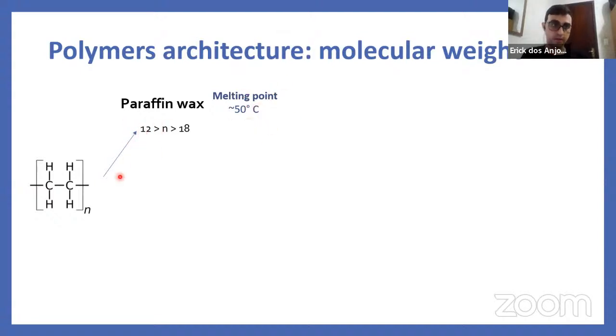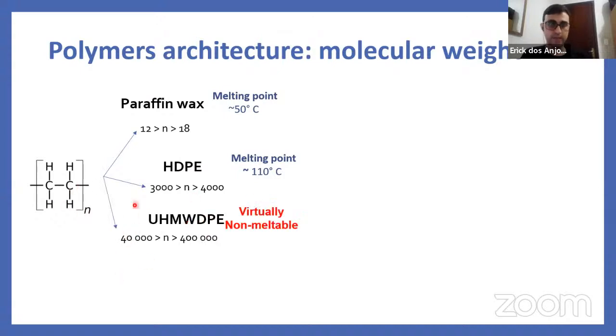If we increase this polymerization index to a higher number, for example, 3,000 to 4,000, we have HDPE, which is a polymer in this case with a melting point around 110 Celsius degrees, almost double that of the paraffin wax, and has excellent mechanical properties, tensile strength and modulus. If we increase the polymerization index even more, we will have a polymer called ultra-high molecular weight polyethylene that is virtually not meltable. So you destroy the polymer before melting it, with a polymerization index much higher than 4,000, for example 400,000. This polymer has extremely good mechanical properties, however, it is really difficult to process, so it's not much commercialized.